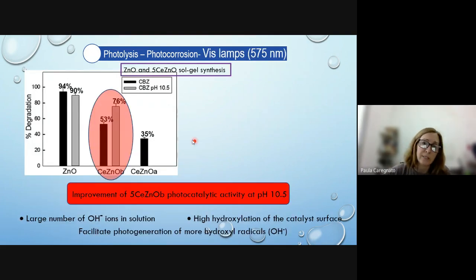Besides, we can see that at the pH of 10, there is an improvement in the photocatalytic activity of this material. At pH of 10, there are a large number of hydroxyl ions in solution, and the catalyst surface is highly hydroxylated. So both effects facilitate the photogeneration of more hydroxyl radicals.